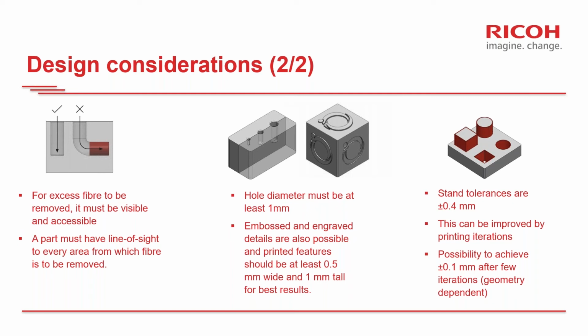In terms of tolerances, the standard tolerances of this process as a first iteration are generally in the range of plus or minus 0.4 millimeter. However, this can be improved by iteration, as depending on part geometry, the level of shrinkage or expansion that you can have during or after the consolidation stage could be different. And in some cases, for a very specific geometry, the process has enabled parts with tolerances of plus or minus 0.1 millimeter after a few iterations.